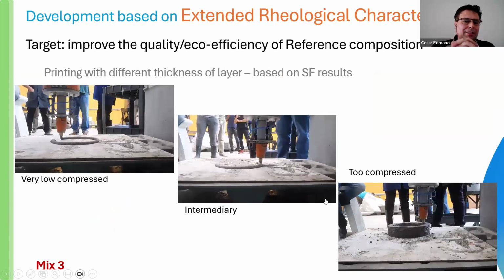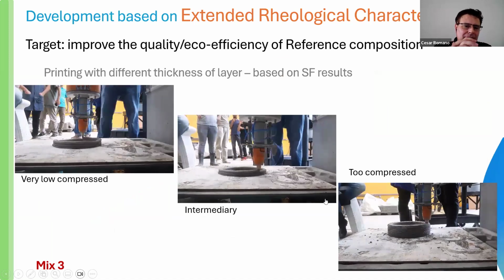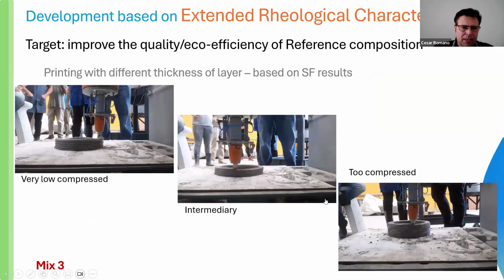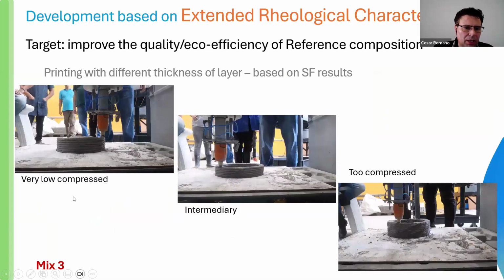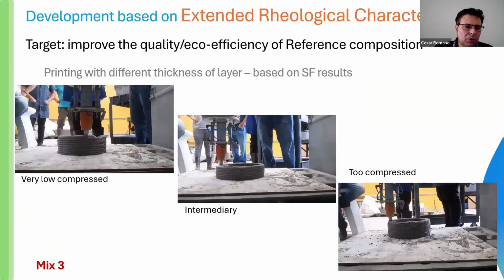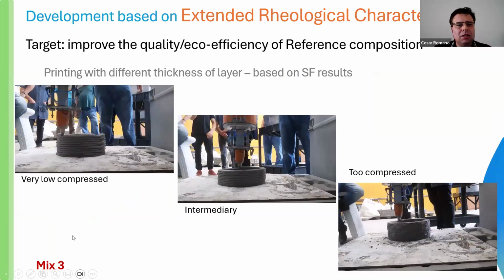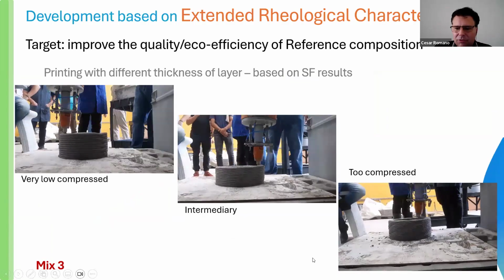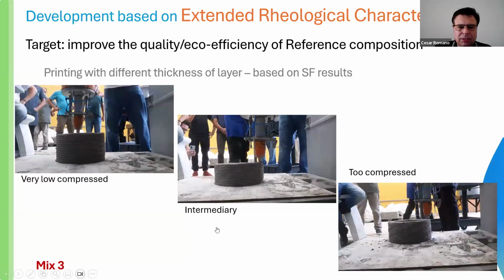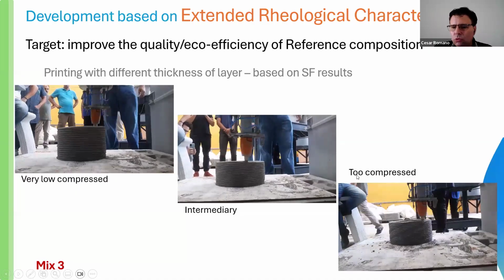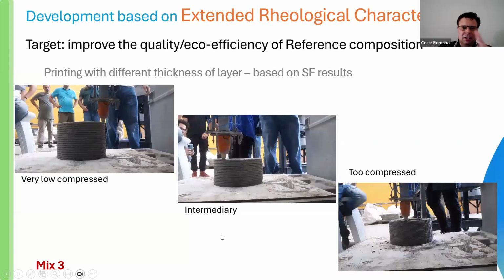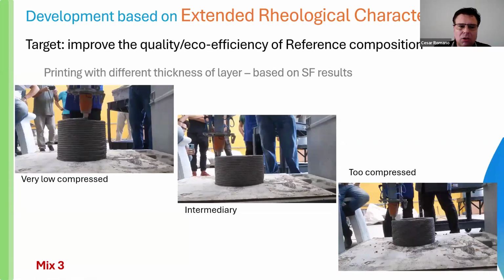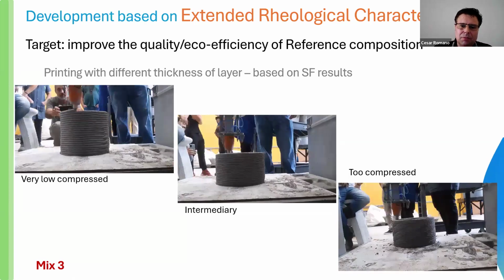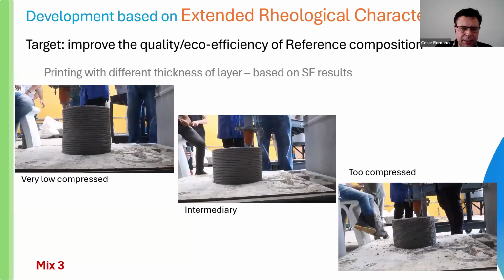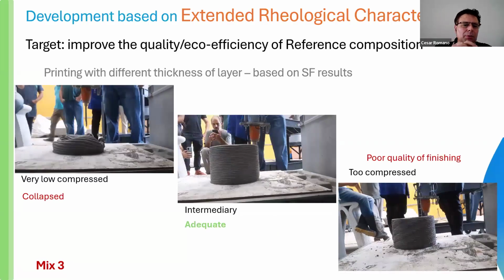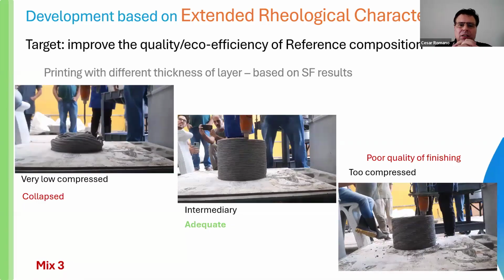Here is an example of the best composition that we evaluated in this work. Here on the left, we produced the piece with very low compression. The layers are higher than the other. This is an intermediary compression, and this is too compressed. You will see all of these are the same batch, all of these are the same composition. And you will see here that we will have a collapse when we use this layer.